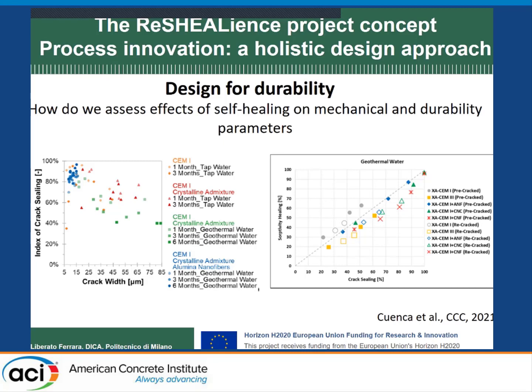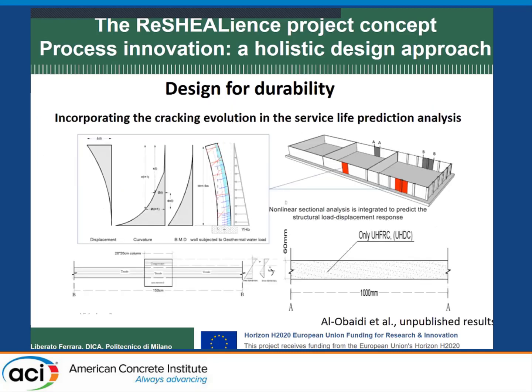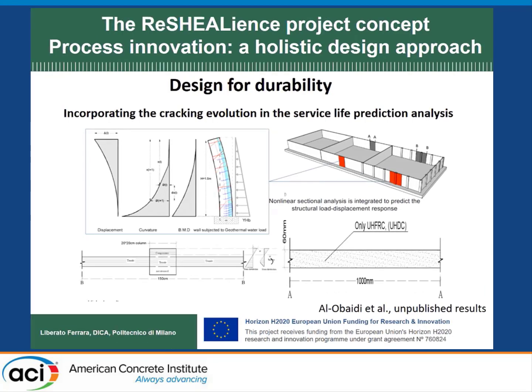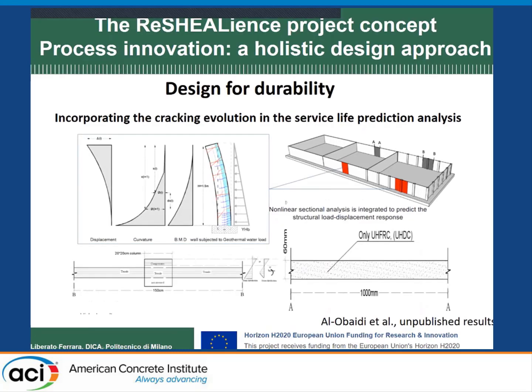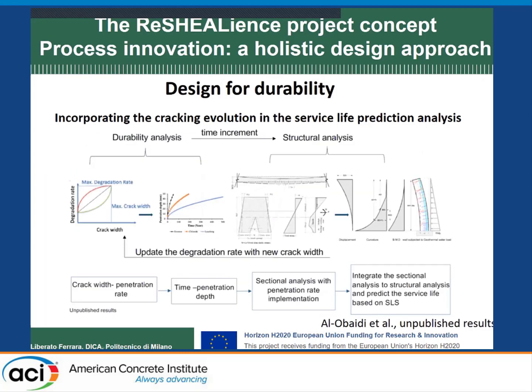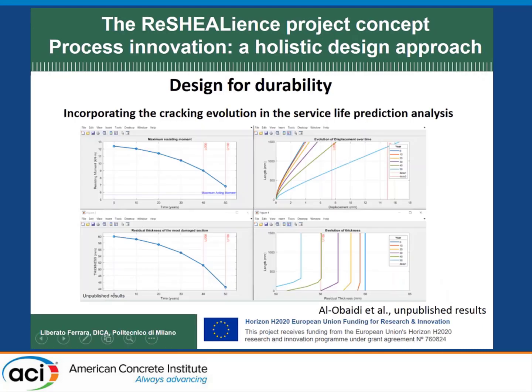So what are we doing now? In the beginning, we started with the evolution of the resisting bending moment just of the critical cross-section. We are now trying to implement this approach into a moment-curvature segmental approach and to extend this to the wall cantilever. You can see the scheme here. So we have the degradation mechanism. We implement it into a cross-sectional model, and we calculate a moment-curvature relationship as affected by degradation. And by integrating this twice over the beam length, we can also calculate the displacement. So these are really quasi real-time elaborations.